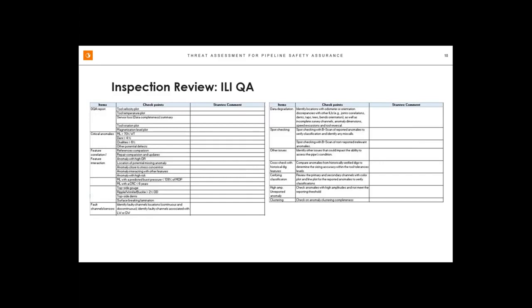So just some examples of the things we look at in our QAQC process. We look at the physical parameters of the inspection run. Was the tool within its velocity constraints the entire run? Were the magnetization levels proper? Were there any critical anomalies that were reported that would require immediate attention or an emergency dig? Are there any signs that there was degraded or missing data? Were all the sensors reporting properly? And then we actually sit down with the ILI vendors and we wind up doing some spot checking. So we'll go through and we'll spot check a few points on the pipeline and say, okay, did the final report reflect accurately what was seen in the raw data, or does there need to be some form of revision made to make sure that the data is accurate?